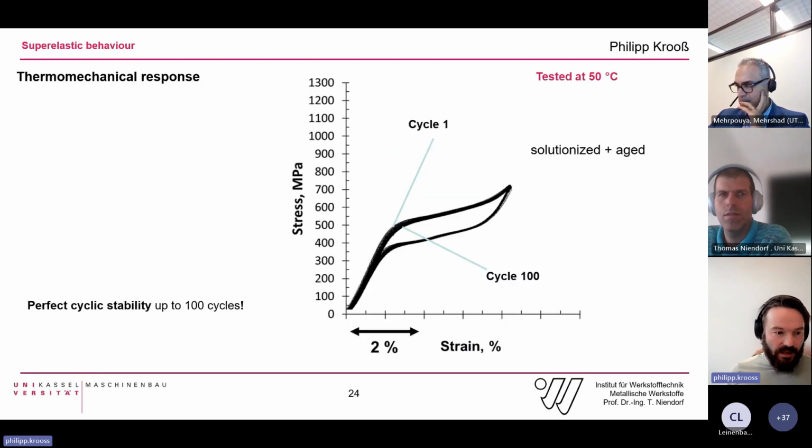We also did some cycling, only up to 100 cycles. I know this is not really representative for any application, but at least we did a test, and we saw that there's almost no functional degradation in this material, so it seems to be stable as well, which is not really in context of the literature, because these titanium carbides are always shown to be detrimental for the reversibility of nickel titanium.